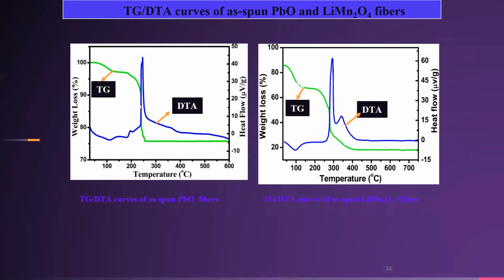Due to that, for further stages, we can see the TG-DTA graphs of as-spun nanofibers of lead oxide and lithium manganese oxide nanofibers, showing at which temperature lead oxide is forming. We can see clearly that above 300 degrees centigrade lead oxide is forming. There is no weight loss above 300 degrees centigrade, which confirms this. Here the green color represents the TG curve, and the blue color represents the DTA curve.